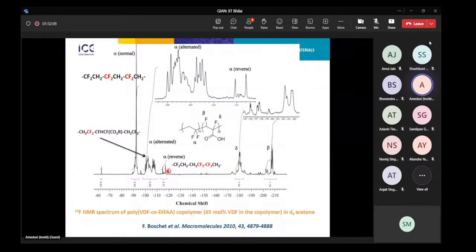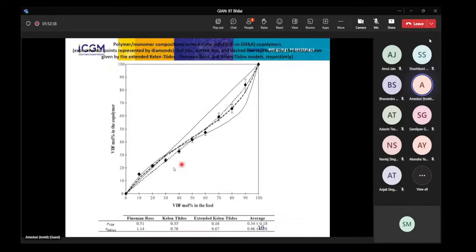And these are the two reverse additions. This is the head-to-head addition. You know, in PVDF, indeed, you have this kind of structure, which is, let's say, 92, 95%. And then you have the reverse addition. So this is a head-to-head, but also then you have tail-to-tail, so CH2 is adjacent to CH2. And these effects are very important because they can make a difference, especially in the thermal stability. So this is an example of how we have been able to figure out the structure of this diagram of composition.